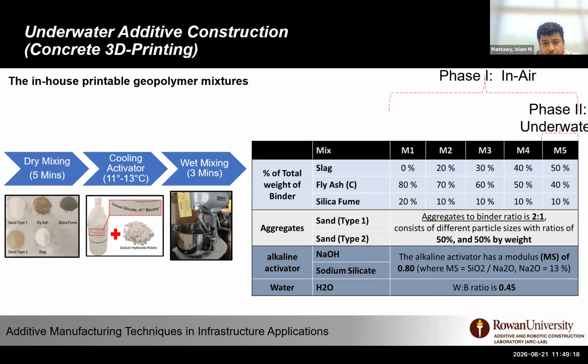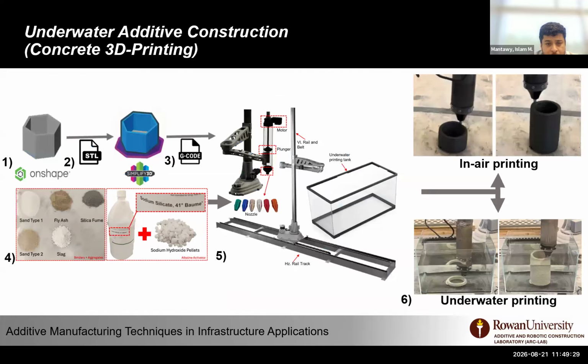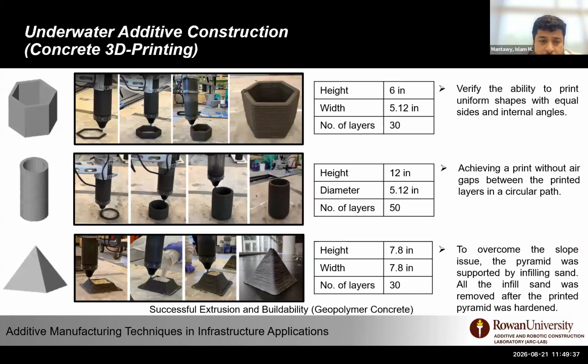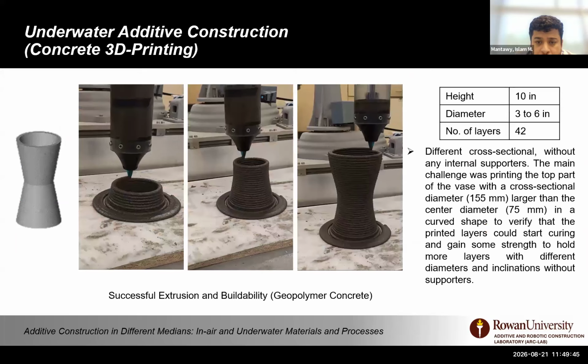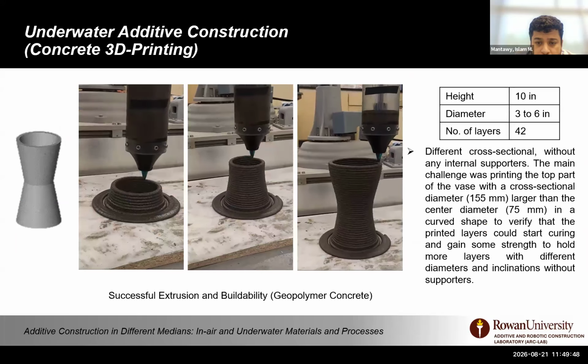So here's our mix, from mix 1 to mix 5, using slag, fly ash, silica fume, different gradations of sand, and a chemical activator in the water. And this is the process we do for underwater printing. We get our water tank, fill it with water, and we print inside. As I mentioned earlier, the material was initially developed for in-air printing and modified for underwater printing.